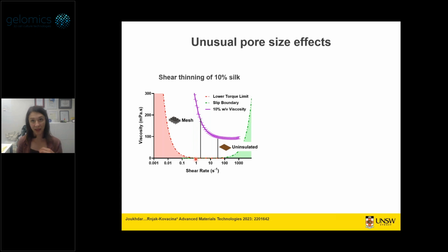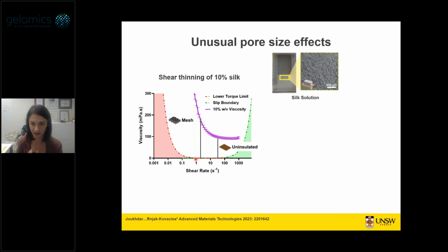And it was the cross-linking of silk that allowed us to actually take this a step further and prove it, because through cross-linking, we could introduce sort of artificial viscosity in low concentrations of silk. So we did not have to work with these 10% silks. We could work with low concentrations of silk. If you take your silk solution at low concentrations, like 2%, you don't get very high resolution pores. You get these very fibrillar structures at very low concentrations of silk.